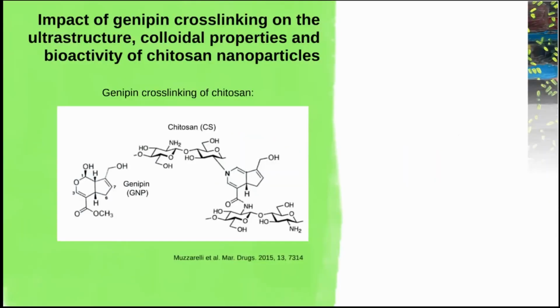The genipin cross-linking reaction of chitosan with genipin involves the nucleophilic attack of a glucosamine residue of chitosan on the heterocyclic ring of genipin, and a secondary amide link formation with another glucosamine residue of chitosan. And we have observed that genipin cross-linking has an impact on the ultrastructure of both genipin co-cross-linked and genipin pre-cross-linked